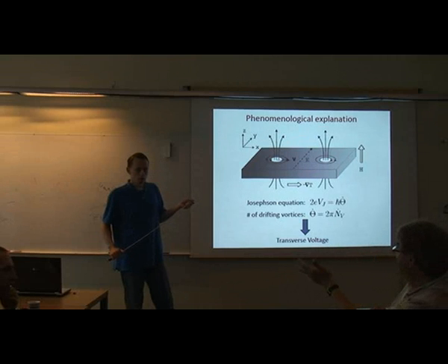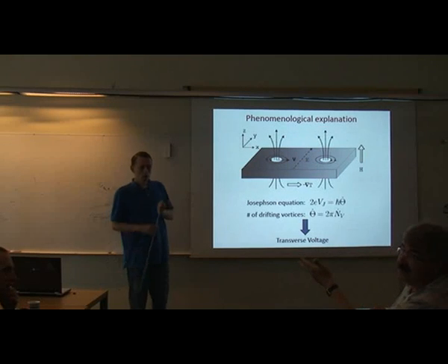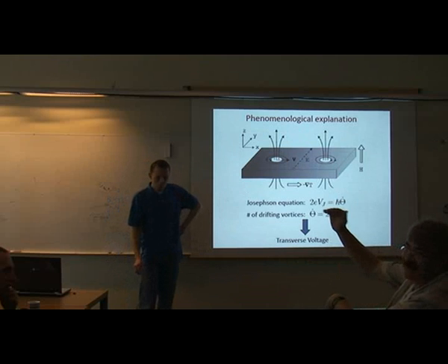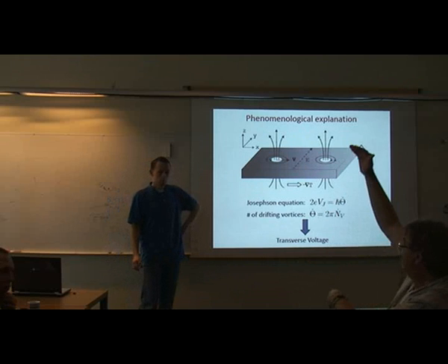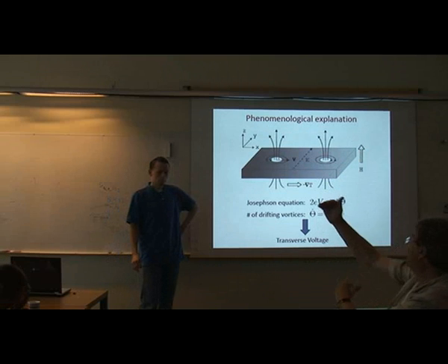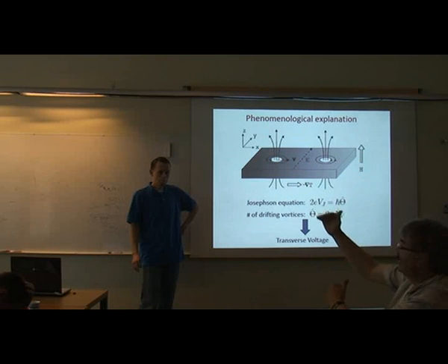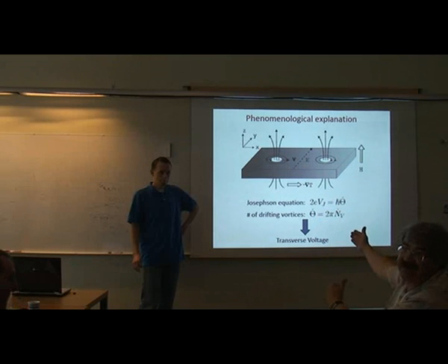You started out with a very nice and clean sample. There's a 90K transition, and then by ion damage, the transition temperature reduces to something like 40K. The regime that opened up there had tremendous Nernst effect, suggesting that by introducing dirt you release this Nernst regime, which makes sense when you think about it.